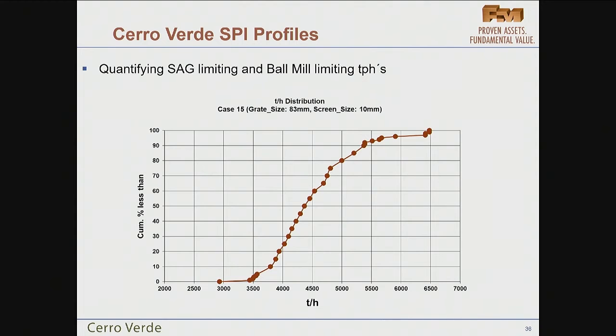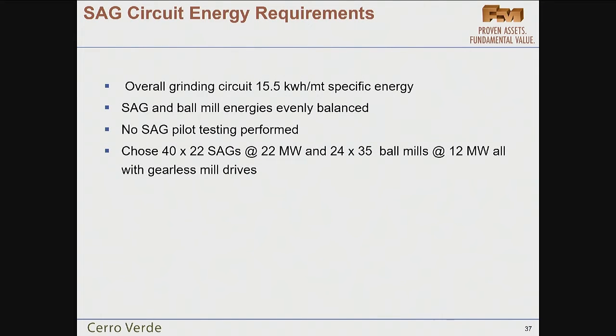But here's a plot that shows the projected SAG throughput. And you could see there's significant portions of SAG mill limiting conditions and ball mill limiting conditions as the interplay between the grinding rates and the mill takes place, just like Chino. Not as extreme, but just like Chino. So advancing with big SAG mills of the day, 40 by 22s and so forth.